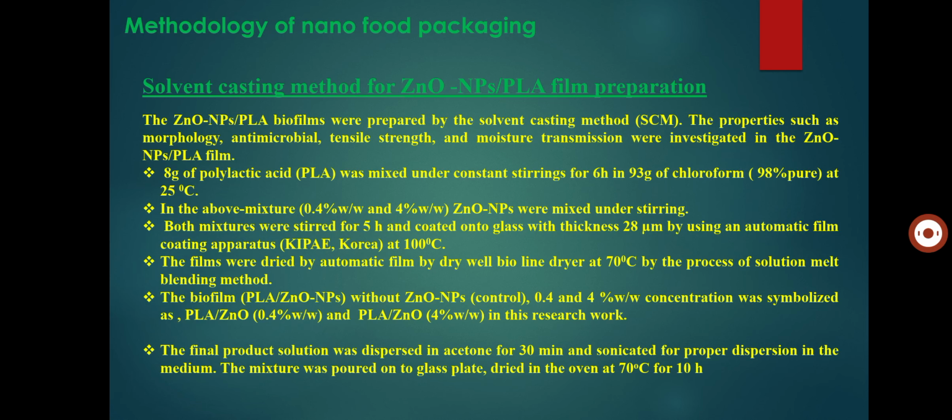And here are some methodology steps in which I use 0.4% and 4% zinc oxide nanoparticles, mixed under stirring, and I use 8 grams of polylactic acid (PLA), stirring for 6 hours in 93 grams of chloroform at 25 degrees centigrade.